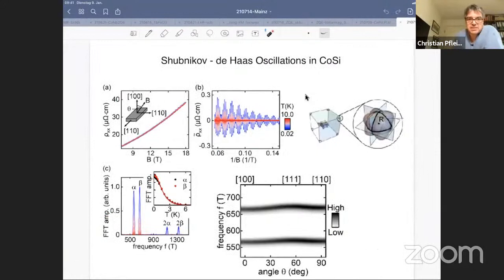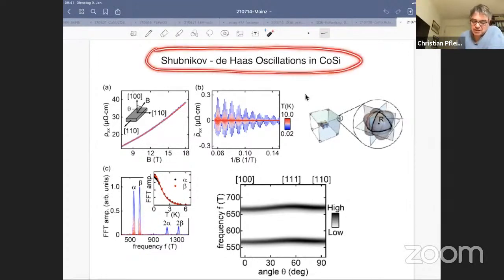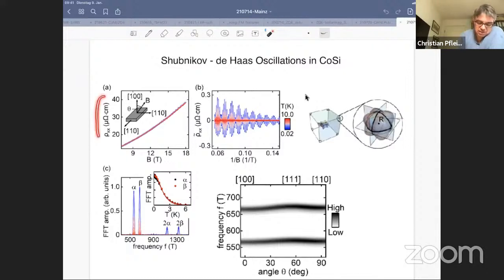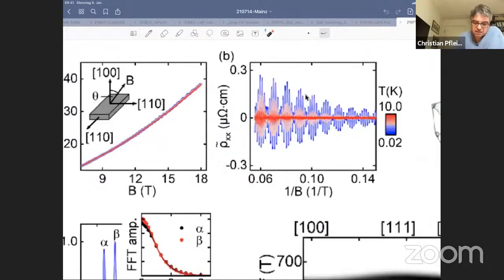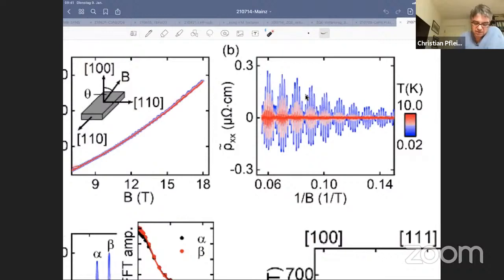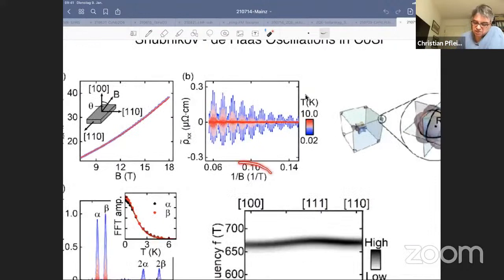What do the experiments say? So now I'm basically back on safe territory. The experiment here is that these were measurements of the Shubnikov-de Haas effect. Shubnikov-de Haas effect is essentially seen in the resistivity or the Hall effect. We measured both, right? So Nico did these measurements as a function of field. You see dominantly the resistivity increasing, but then when you zoom in, you see that there are some wiggles on there, right? So you subtract something from the background, and then you plot it as a function of 1 over B, and you find there are these oscillations.